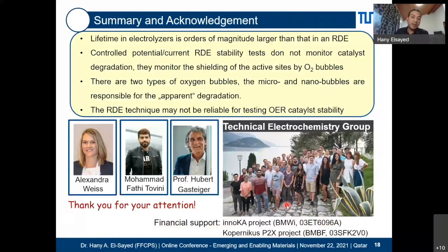Well, I think now I can conclude basically with this. I'm not going to read through this, but I just want to clarify that we're not saying people should not use RDE. And we're not only specific on RDE. I think we're really talking in general about any liquid electrolyte method that we can use to study any gas evolving electrode. I'm not even specific about oxygen evolution, but any gas evolving electrode, specifically during the stability. Activity can be obtained, but the stability has to be treated really with careful caution.